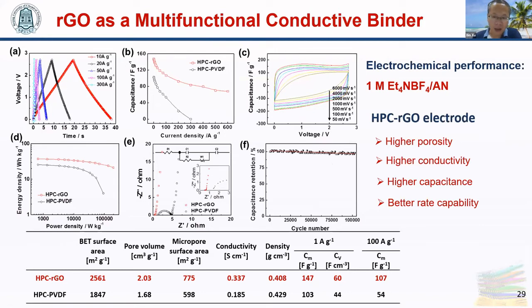We can see that the rGO bonded electrode shows larger surface area, larger pore volume, and higher conductivity, and the capacitance is 40% larger than the conventional PVDF bonded electrode. And especially the rate performance is outstanding. It can endure a very large current density of 600 amperes per gram.